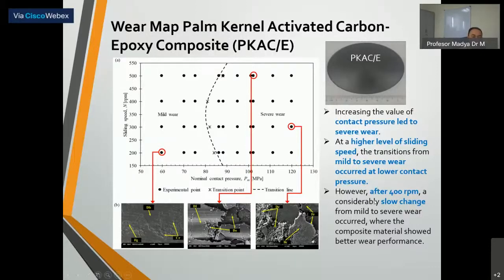However, after 400 RPM, a considerably slower change from mild to severe wear occurs, where the composite material shows better wear performance. Actually, the wear map is beneficial for the material engineer or design engineer to fabricate and produce the product without prior failure.